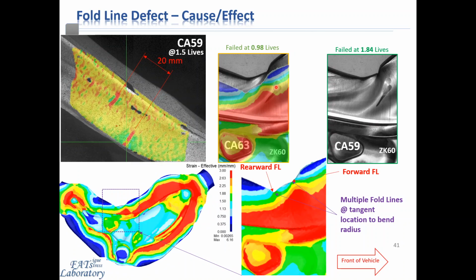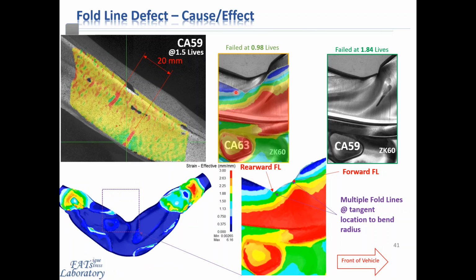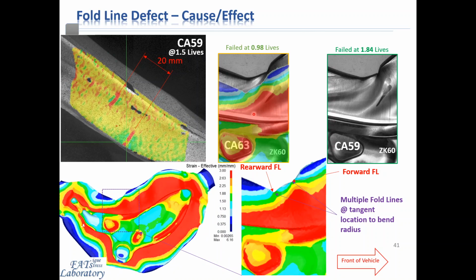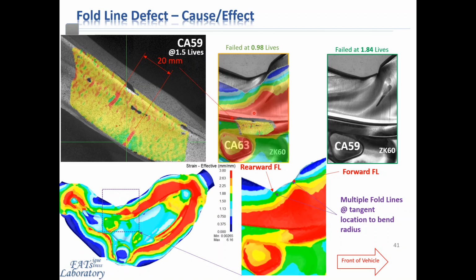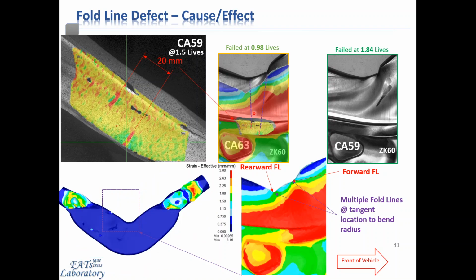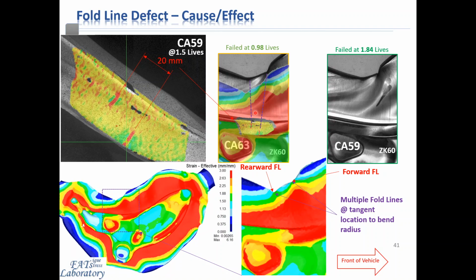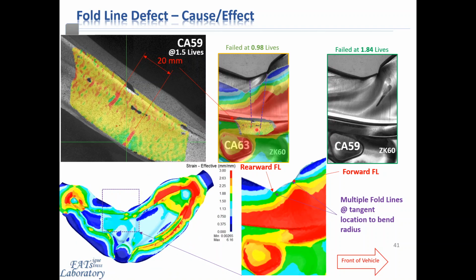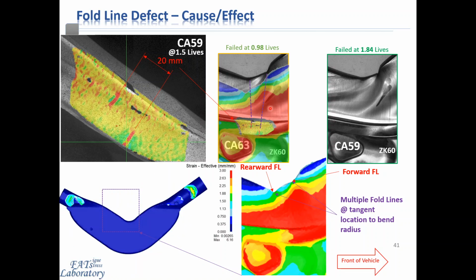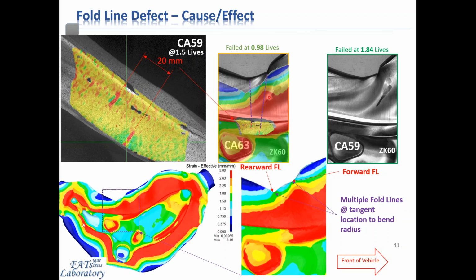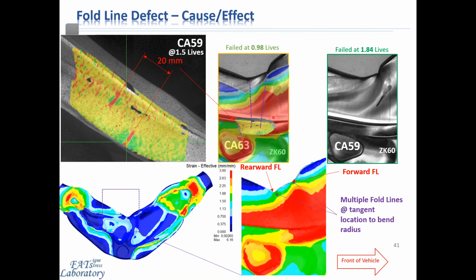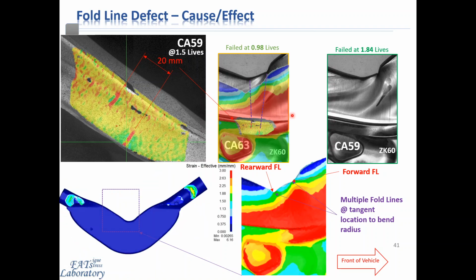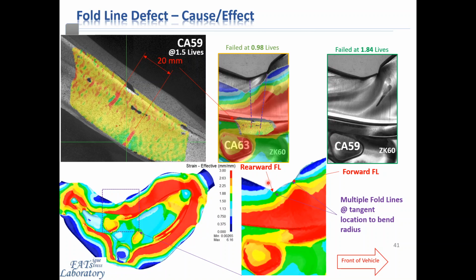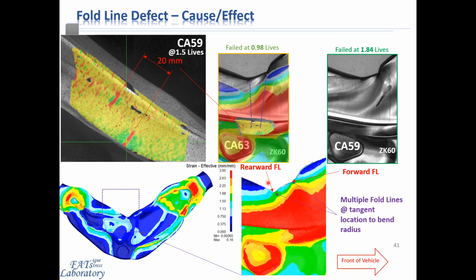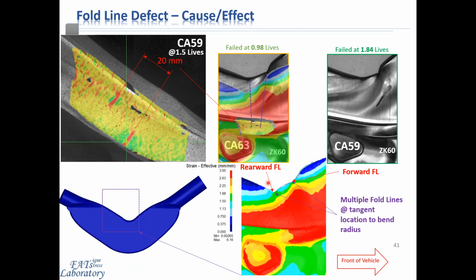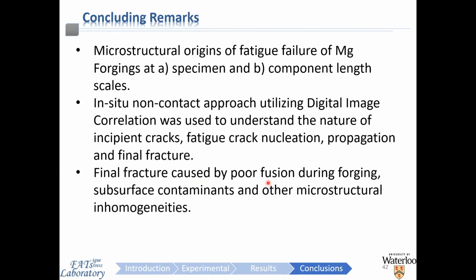Now taking one of the full field strain observations and mapping it directly to this location here in the component, we can see that the two locations where the strain localized during fatigue testing can be traced back to these fold lines in the forging. So if we extend these lines from these fatigue cracks, they approximately line up with the fold apexes that are within the forged component prior to machining, in addition to agreeing well with the forging simulation prediction below. So this provides good evidence of the microstructural origin of these fold line defects and how they manifest themselves in fatigue failure. So, some concluding remarks.